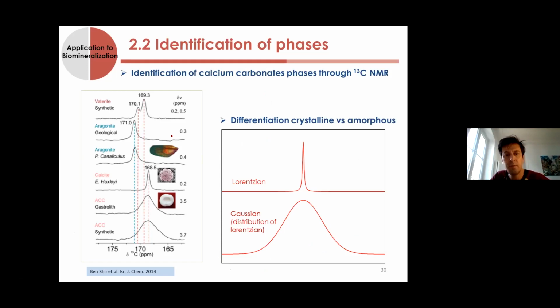So it works well with the calcium phosphate, but it works well also with the calcium carbonates. You have 3 different polymorphs in the case of calcium carbonates: vaterite, aragonite, and calcite. You see also that you have some differences in terms of chemical shift for the carbon - this, of course, is carbon NMR. And you see that you distinguish also here the 2 different chemical environments in the case of vaterite.